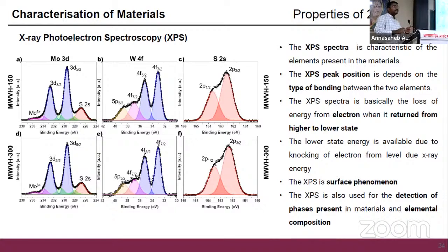Depending on the bonding, in XPS we look at the electron ejected from the material, and the environment from which the electron is ejected will affect the binding energy of that electron. So if tungsten is surrounded by sulfur, the environment is different than if tungsten is surrounded by another tungsten. Since the environments differ, there will be a big difference between the electrons emitted from these two different conditions.